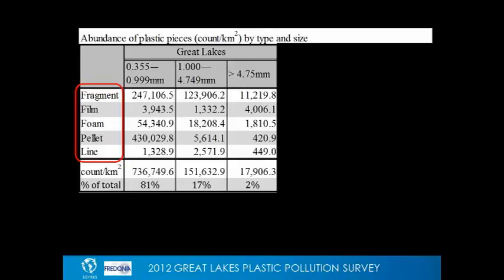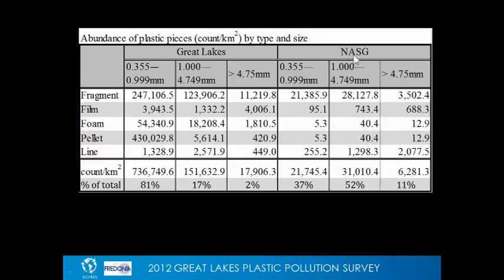And what I want to talk about is comparing our numbers here in the Great Lakes to numbers obtained in the North Atlantic Gyre. Because remember, the Great Lakes are upstream essentially from what we're seeing in the North Atlantic Gyre. I didn't do the North Atlantic sampling; this is my colleagues at the Five Gyres Institute. So we're comparing the numbers from our sampling expedition here in the Great Lakes in 2012 to those obtained during one of their expeditions in the North Atlantic Gyre. What was really interesting to us is that in the North Atlantic Gyre, the majority of what you find is about 1 to 5 millimeters in diameter.